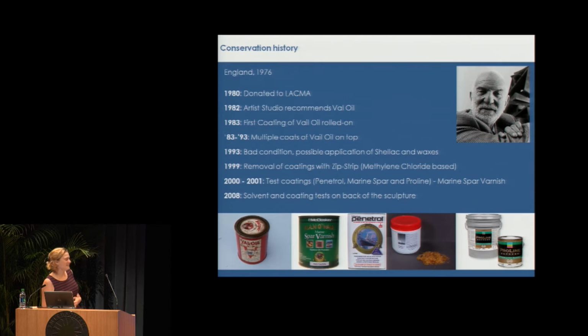So what happened was in 1993, I got another report stating that the object was in really, really bad condition, and that on top of that, they added more waxes and shellac. But I'm not sure what they meant with shellac, so I'm not really sure if it was really shellac. So in 1999, the conservator decided to start a major treatment. And the coatings were removed with zip strip, which is a paint stripper based on methylene chloride. And the steel plates were all detached from each other and re-welded with bead welding technique, so the water could be easily drained in between the plates.